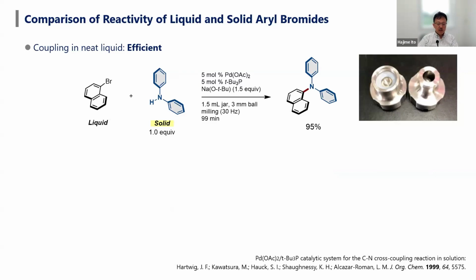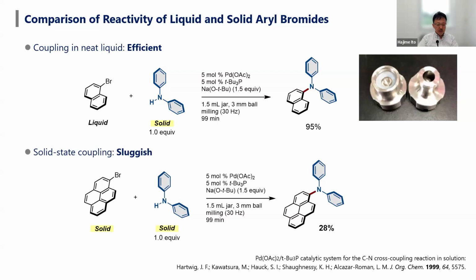We first tested the reaction between liquid starting materials and solid starting materials. This reaction expectedly worked very well using ball milling. However, if you want to make a reaction between two solid materials, the reaction did not proceed very well, and because of the decomposition of the palladium catalyst, only 28% product yield was found.